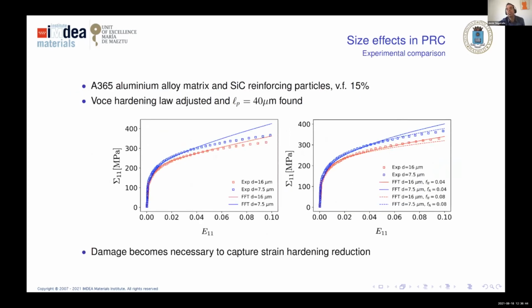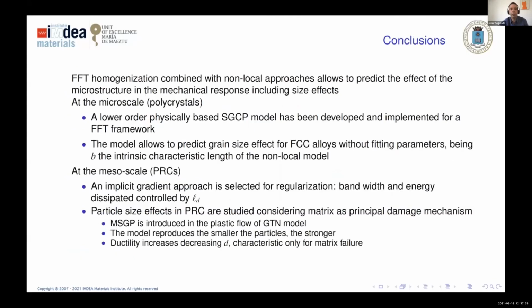So how does this fit with experiments? In this case, we have a quite phenomenological model, so we have to fit parameters. And what we observe is that if we fit just plasticity without damage, we are not able to predict the response for large strains, but we predict well the particle size effect. And if with this model fitted up to here, we just include the damaging part, we are then able to capture the first part where damage is not playing any role, where we have the particle size effect, and the second part where the size effect in damage plays a fundamental role. Okay, that's what we have done.